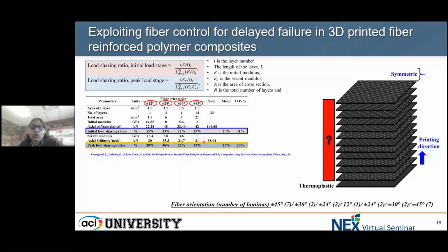So if we look at the load sharing ratio, we came up with a design in order to have the least variation between layers. This was our most preliminary design, and you will see that as the work progressed, we've been able to achieve very, very good designs in terms of the variation of the axial stiffness. So if you had 12 degrees, 24 degrees, 30 and 45 with so many number of layers, we were able to achieve about a 30% variation in the axial stiffness. That gave us a design of basically the stacking sequence and the print direction that we were able to embed into the 3D printer.